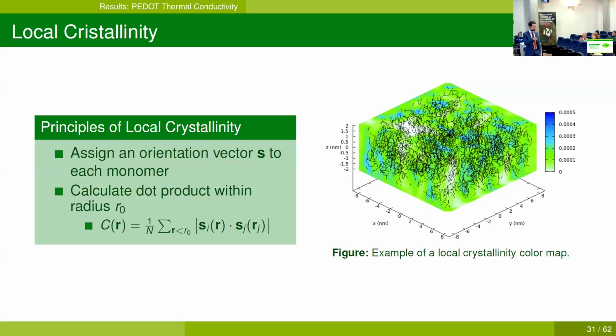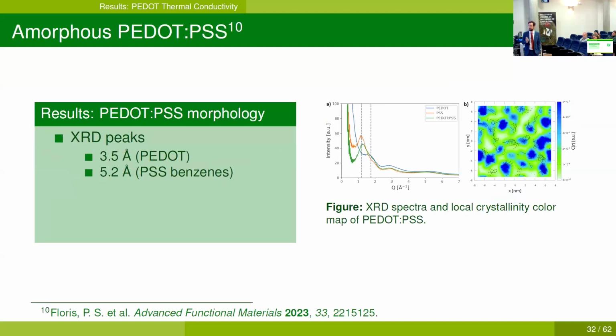And we assign a value to each point in a grid that we define in the sample. And we are able to graph a color map where we can see the points in the sample where the chains are most aligned, since the dot product will be maximum where the chains are aligned. Once we've introduced this, we see that we have also calculated the simulated X-ray diffraction patterns for PEDOT:PSS. And there's a 3.5 angstrom PEDOT peak here, and here for PSS benzene a pi distance of 5.2 angstroms, which is in agreement with the literature.